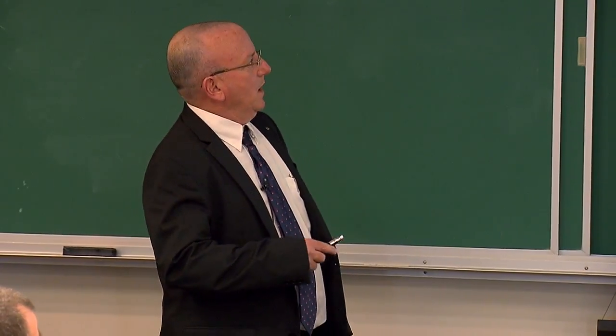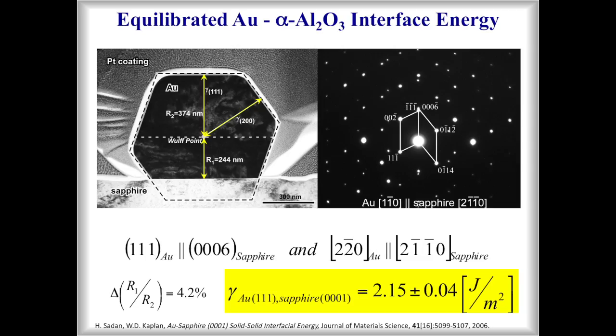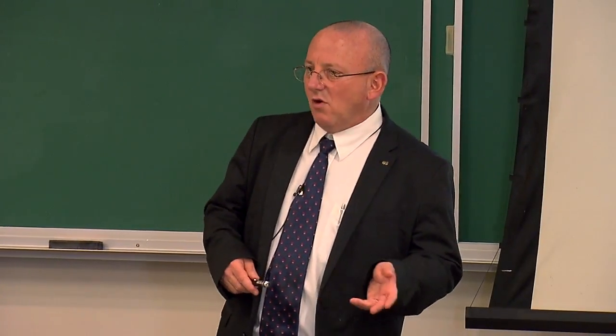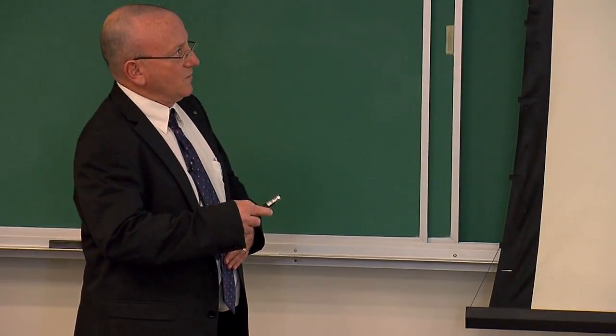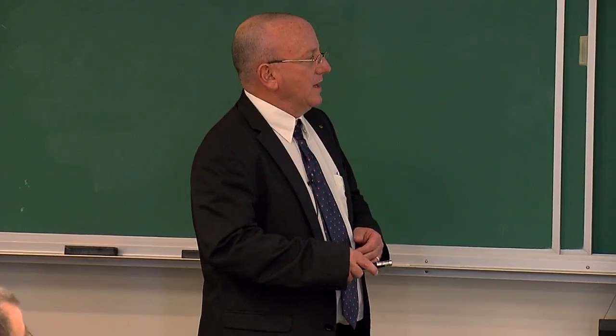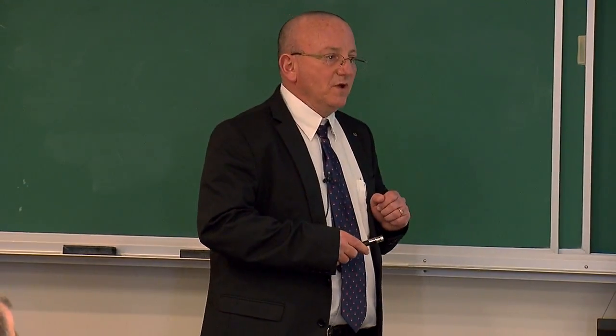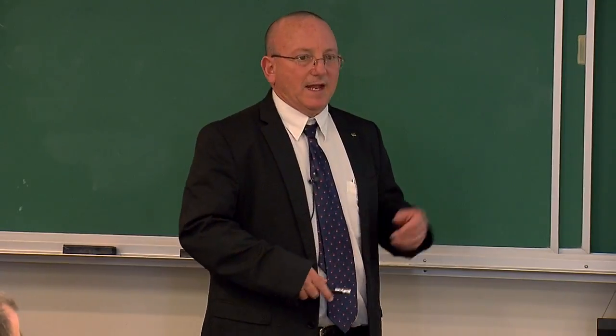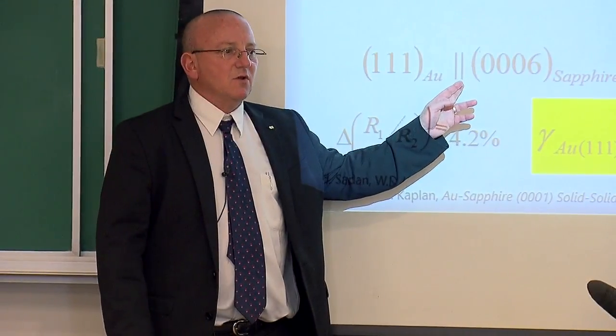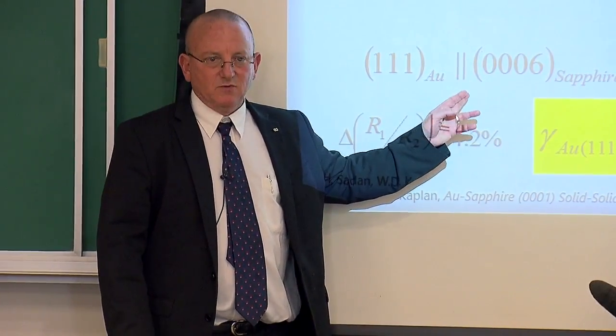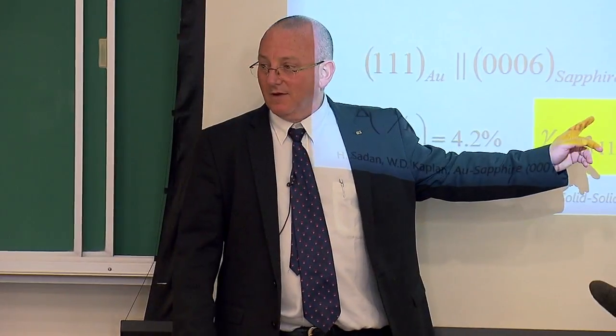So we reached equilibrium. This is gold, basal plane of sapphire. The interface is flat. It's coplanar with that of the surface, which is the same condition for Young's equation. And we measured these relative distances, and we can work out the relative interface energy. In this case, the surface energy of sapphire we measured independently, and the surface energy of gold has been measured by many people. We use the 111 surface facet, which is 1.4 joules per meter squared, and we can get out the absolute interface energy for a specific low index orientation relationship, which is listed here. That low index orientation relationship, by chance, is also the low energy orientation relationship, which exists at equilibrium. This value, of course, is only for that one. It's not for any general orientation that you would happen to find.